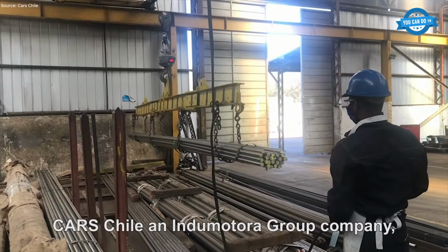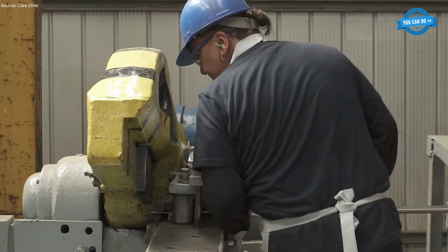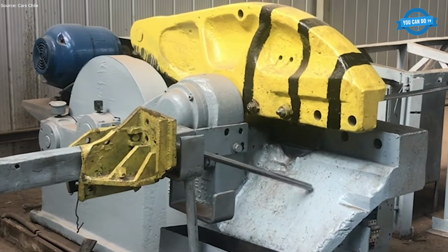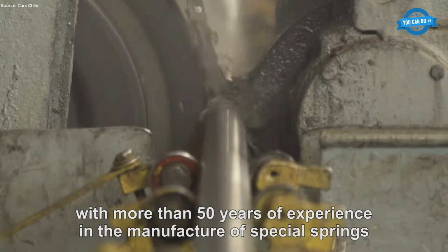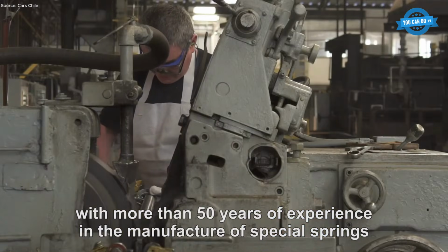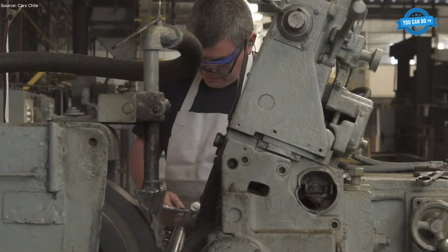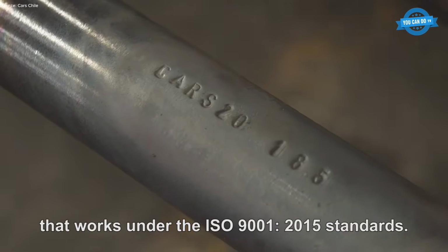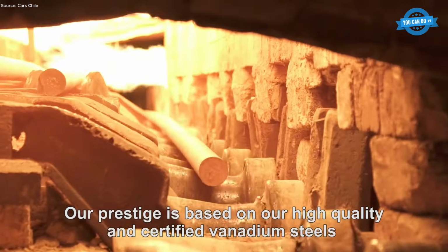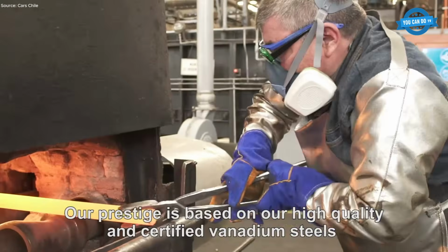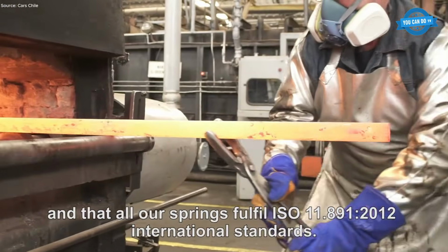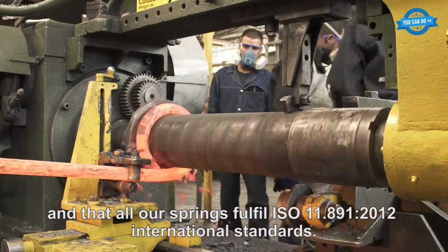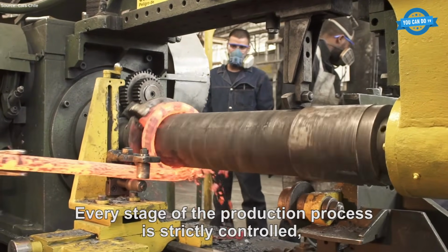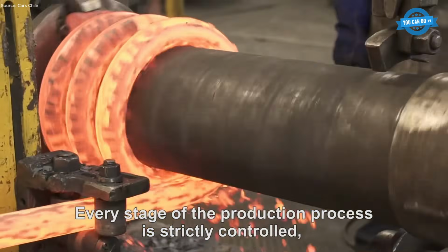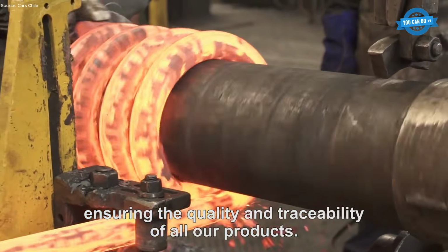In mining, a single spring failure can halt an entire operation, so performance is engineered long before the first load is ever applied. Manufacturing begins with certified high-grade alloy steel selected for controlled chemical composition and mechanical performance. The hot coiling process is executed within calibrated temperature ranges to maintain grain structure integrity. Immediately following forming, springs undergo precisely monitored quenching and tempering cycles. These heat treatment stages are controlled through advanced thermal systems to achieve the required hardness, tensile strength, toughness, and elastic recovery while relieving internal stresses.